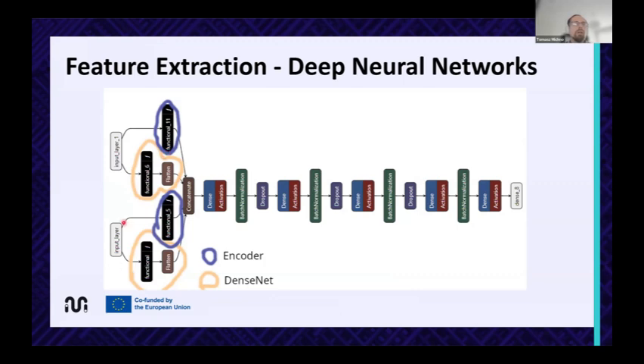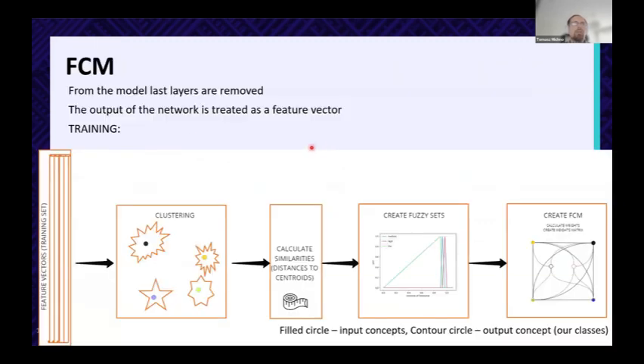What is the main core of the feature extractor is the encoder. So we trained an autoencoder on training images, and then we extracted only the encoder part. And also we have a trained dense network, and we concatenated all four parts, so 2 parts per one type of image, into one network, and then we trained everything together, and as a result we got some classifications, but as a feature extractor we just removed some last layers of the network and then used the output as features.